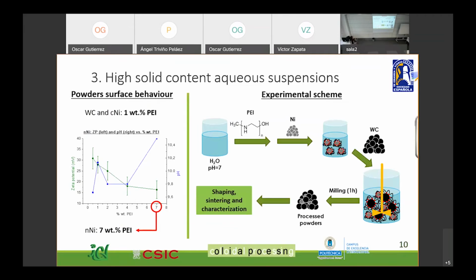So here there's a general scheme of the experimental procedure we carried out in the lab. As we can appreciate here, after the addition of the dispersant, nickel powders, and finally our base material, tungsten carbide powders, they were milled for an hour, and after that, the processed powders were dried. So they were ready for the next shaping, sintering, and characterization steps.